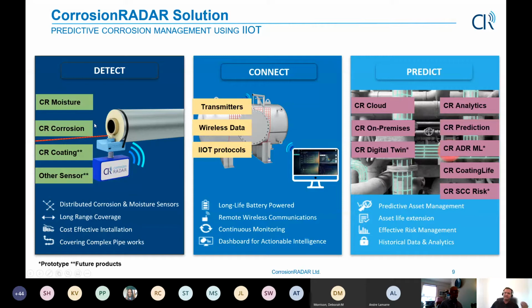of data is. If you monitor moisture, it does not mean you just get information about moisture. You get information about various aspects, like what is the potential likelihood of corrosion rate, what is the coating life reduction, say if you have models, what is the risk of stress corrosion cracking, and so on. So the combined corrosion and moisture can give a whole lot of information, whether there is a risk of chlorides, because chloride leads to a lot of accelerated corrosion. So corrosion rate may be high there, and moisture presence.